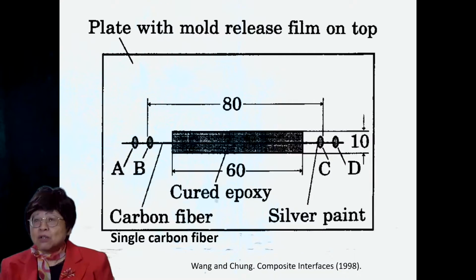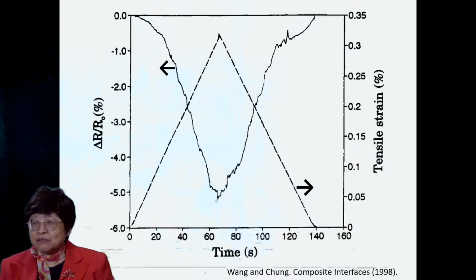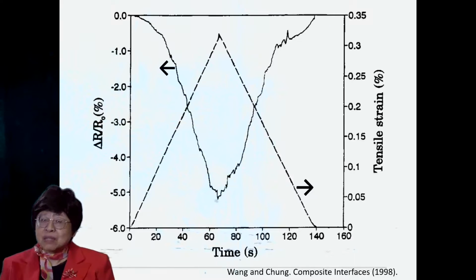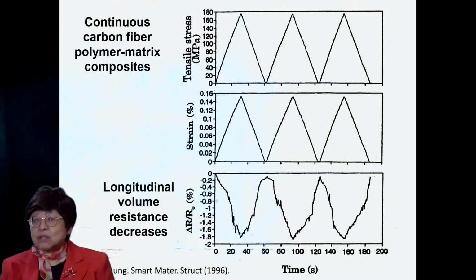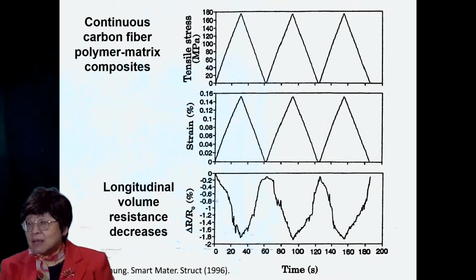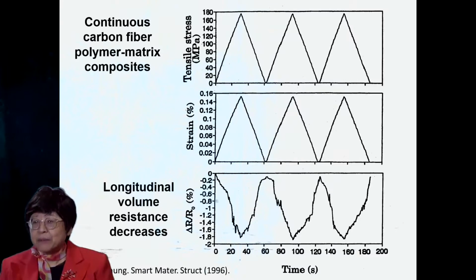And we do this measurement during tension on the single fiber. And indeed, during tension, the resistivity of the single fiber decreases, and it's reversible upon unloading. And this decrease in the resistance is because the tension is canceling out the compressive residual stress in the fiber. And this extends to the behavior of a laminate with continuous carbon fiber in epoxy. At the bottom, it shows the longitudinal volume resistance. It indeed decreases and is quite reversible, just like what we saw in the case of a single fiber.